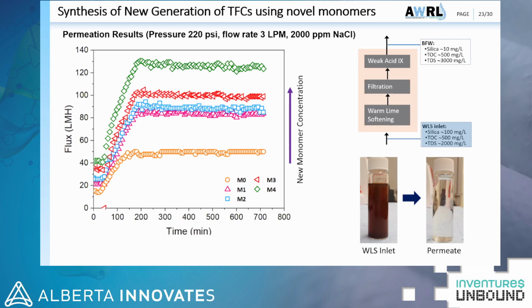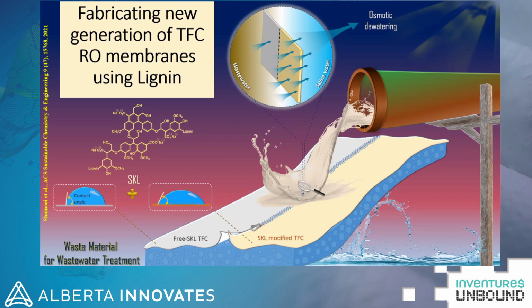The final work is to make lignin-based RO membranes. It is a novel study in which we use lignin for making membranes, and we call them greener membranes. First, lignin was dissolved in DI water, then MPD was added to this solution. After that, fabrication of the TFC membrane starts by the conventional method, by soaking the PES support with the MPD-lignin solution. And after that, the TMC solution was poured on the soaked support to allow for the polymerization reaction.